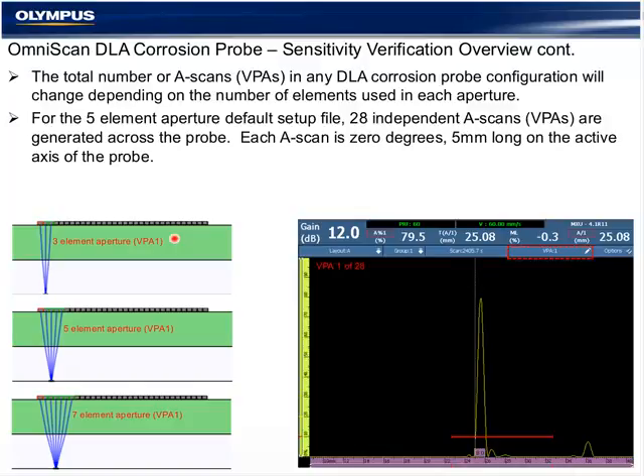So the most common version of that, designed for 2 to 25 millimeter thicknesses, results in 28 independent A scans. And we can see that depending on which of the 3 you selected, it'll be a slight difference in coverage if you're measuring beam center point to beam center point within the probe.